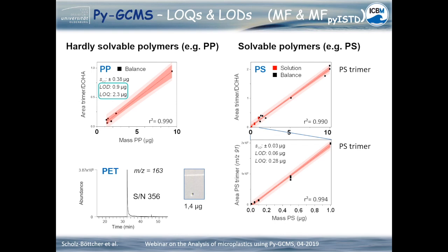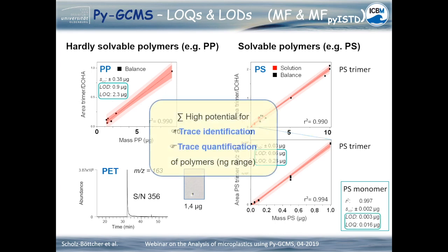And here also the combination of solved standard and standards using the balance is shown quite nicely. Looking at the lowest calibration end, LODs and LOQs in the nanogram range are visible for the styrene trimer and even much lower for the styrene monomer, where the limit of detection is 3 nanograms. Overall, the method shows a high potential for trace identification and trace quantification of polymers in a nanogram range.